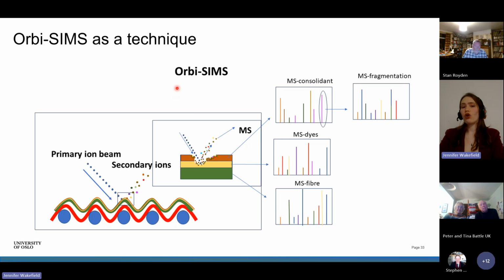And with the OrbiSIMS, you can also do a depth analysis. So if there is a coating of consolidant over the material, you could theoretically go through that layer onto the actual fibers to identify the dyes. And you can also do this fragmentation pattern of each individual compound, like with the LCMS, to give you, again, this fragmentation pattern that you can search through databases.